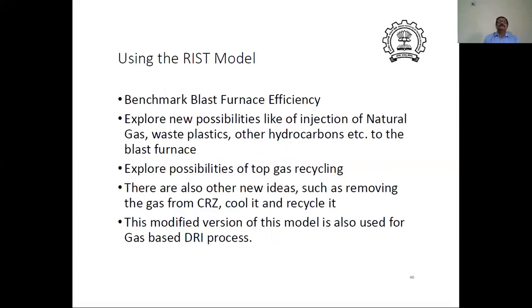So this simple model can be used to benchmark blast furnace efficiency, explore new possibilities, as I told you, and even look at top gas recycling. Okay? Let me also tell you about one of the ideas which Professor Ballal of IIT Bombay has been telling. There are some experiments which were done in Europe to recycle the gas back, because it contains 20% CO and 20% CO2. So remove the CO2 and put the CO back into the furnace so that your coke rate, carbon rate, can come down. Unfortunately, this is the reason I went to the north of Sweden, because they have an experimental blast furnace.